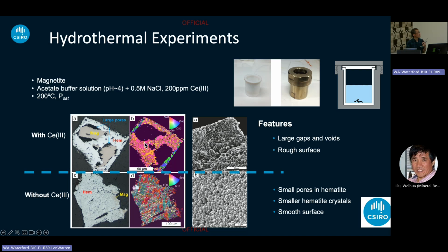And this is the reconstructed grain distribution from EBSD analysis. When you have no cerium, no rare earths, in the same conditions replacing magnetite, you get totally different textures, with very different surface structures and also different grain sizes.